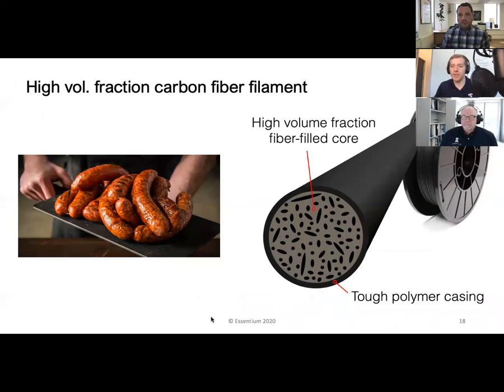Moving into advanced materials, another thing we've been innovating on, as Josh mentioned, is the next generation of additive materials and additive composites. We've created a technique on our production lines to create multi-layer filament, where we can deposit multiple layers, core shell, into a filament structure when we produce the filament. One of the cool things that's allowed us to do is create materials that normally were not even possible to turn into filament.